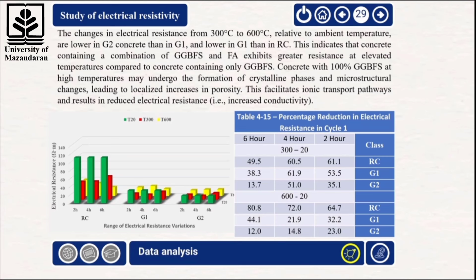The table presenting the percentage reduction in electrical resistivity after one thermal cycle shows the results for RC, G1, and G2 at holding times of 2, 4, and 6 hours. As can be observed, RC experienced the greatest reduction in resistivity.